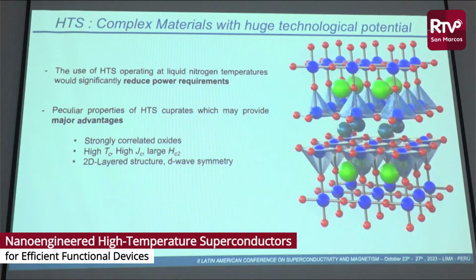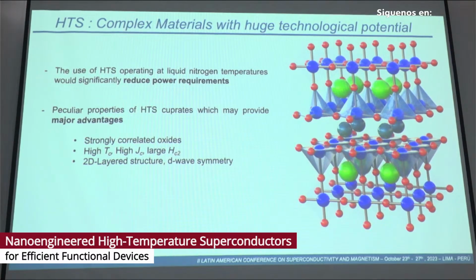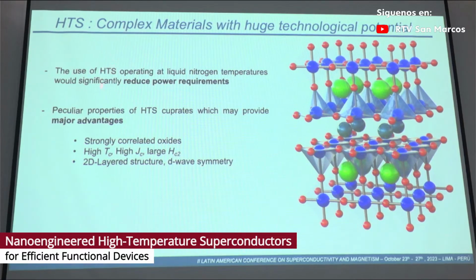But in our group, we are trying to work with high TC superconductors. With high TC superconductors, we can use nitrogen to refrigerate the system, so we reduce the power requirement for the system. And also, there are several properties that high TC superconductors may introduce in order to improve the efficiency and the functionality of the devices. For example, these materials are strongly correlated oxides with peculiar properties. They have high TC, high JC, and large HC2. They can work with higher fields and higher currents. And also they have a proper 2D structure and d-wave symmetry that can be tuned in order to modulate the performance of the materials.